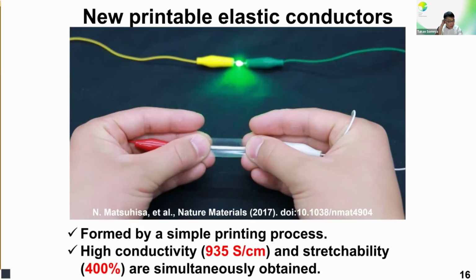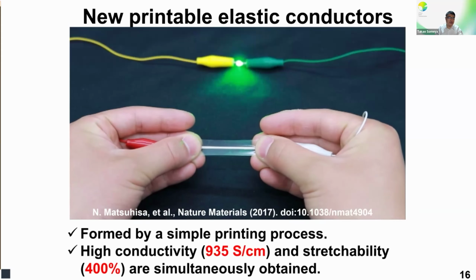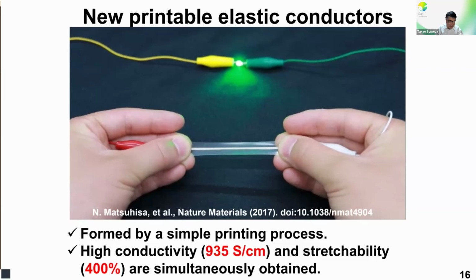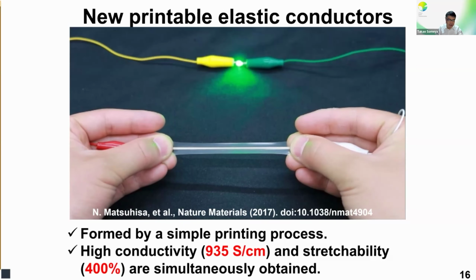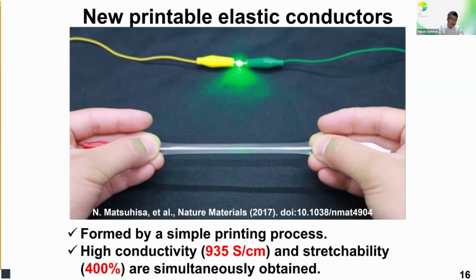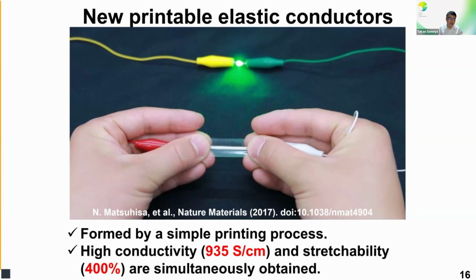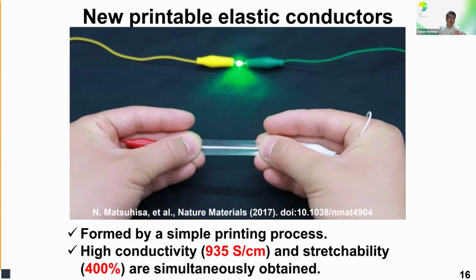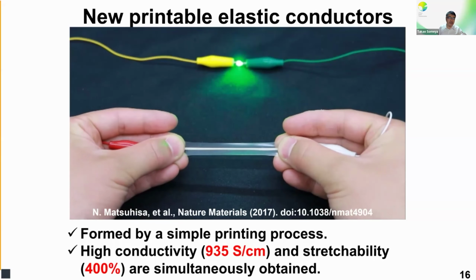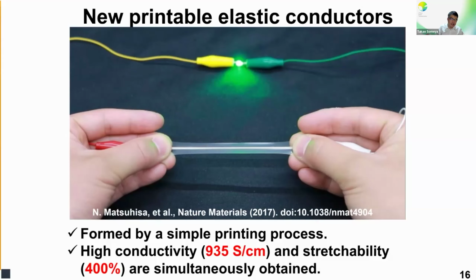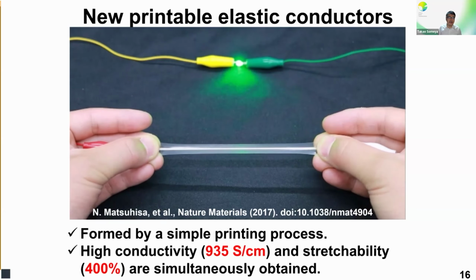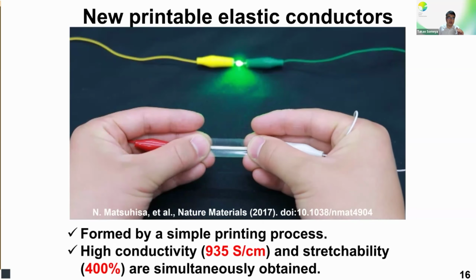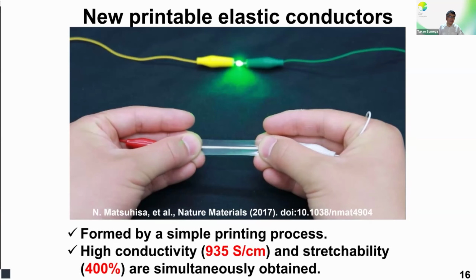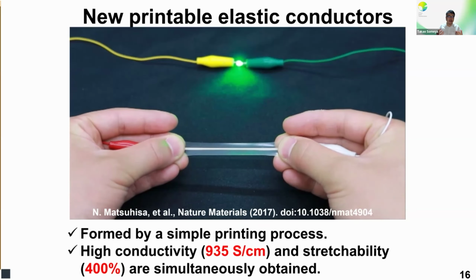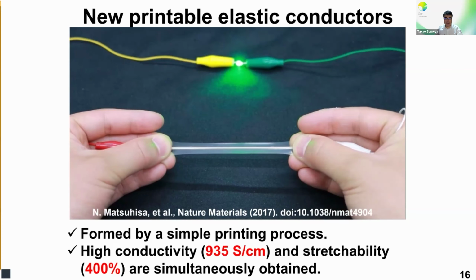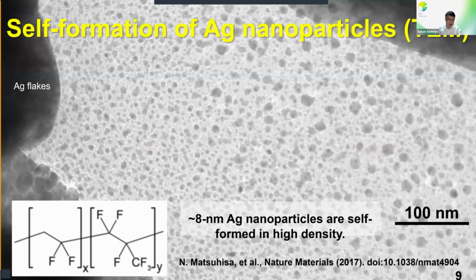So our printable elastic conductor achieved a high conductivity close to 1000 siemens per centimeter and stretchability over 400% simultaneously. So you may see even though we stretch our material substantially, the brightness or light intensity didn't change at all. This means even though we stretch our device substantially, the change of resistivity could be suppressed. So in that way, we can utilize the elastic conductor to make the stretchable integrated circuit.